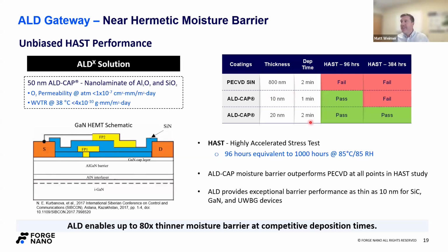And so, we put the deposition time here as a column to highlight that we're actually faster and have better performance. To pass their spec, they wanted 384 hours. We did that with 20 nanometers, and it takes about 2 minutes. The eventual application for this customer was 50 nanometers, but they wanted some extra security. What I want to stress for people is, PECVD is great because you know it, but it might not be great for what you're using it for.